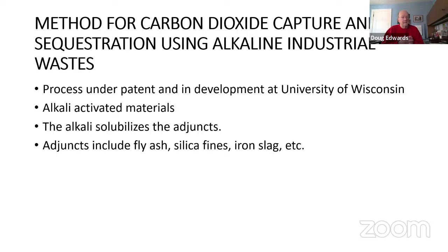I mentioned this earlier, you may remember the term alkali activated material. So the alkali, again, is used to solubilize the adjuncts. So you're adding a bunch of things together, getting them to interact with one another and to precipitate out a product that can be used as an alternative to Portland cement. And these adjuncts that are added include fly ash, which we've talked about quite a bit, silica fines, and iron slag. And I mentioned that there's a lot of fly ash out there.